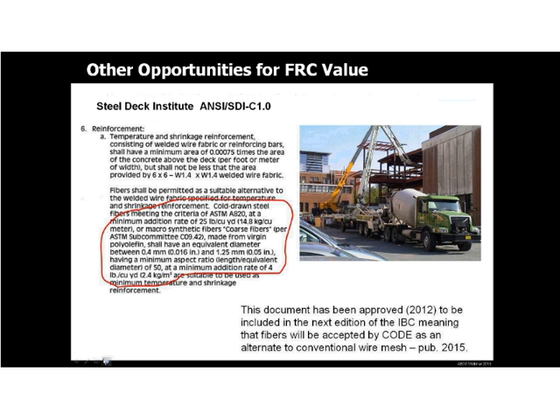Another application for value, as discussed earlier, is a change that will be implemented into the building code. This document from the Steel Deck Institute in regards to the use of temperature and shrinkage reinforcing for composite steel deck design, going forward, this document has been accepted into the building code and will be published in 2015. And as you can see on the left side of the screen, the use of a minimum of 25 pounds per cubic yard of steel fibers or a minimum of 4 pounds per cubic yard of macrosynthetics may be used to replace temperature and shrinkage steel for composite steel deck construction. Again, a cost savings, a safety savings, and a time saving on a project.